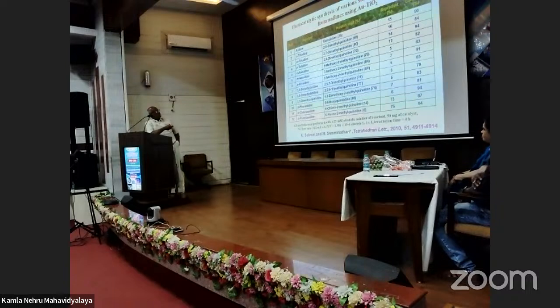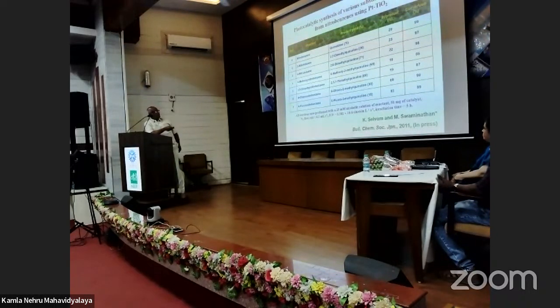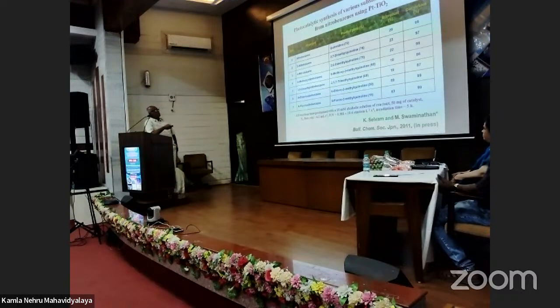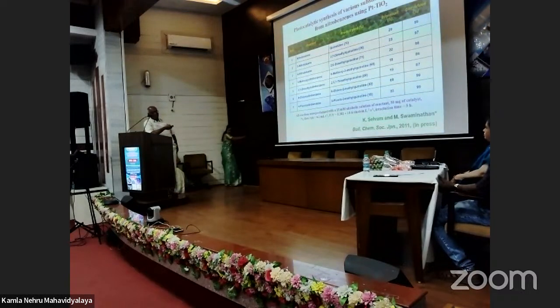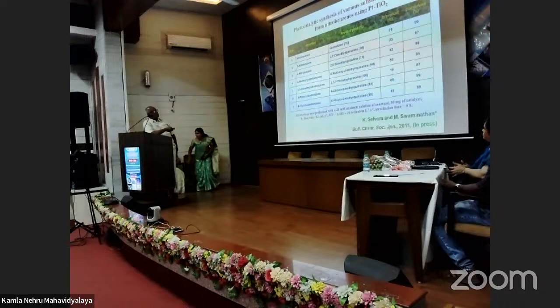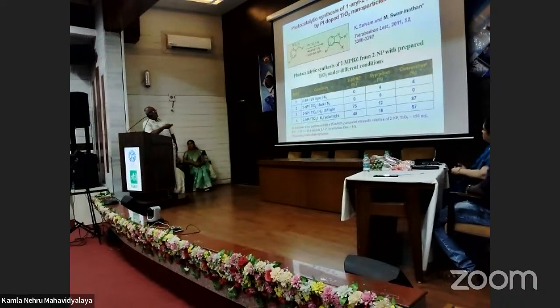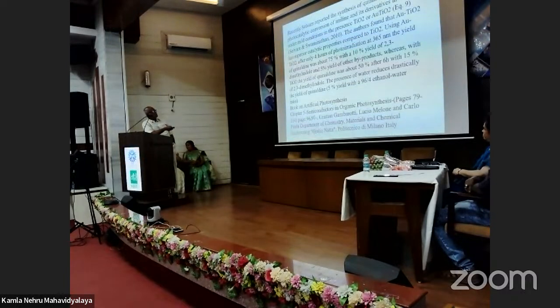And similarly, it's not only nitrobenzene; we can also take aniline directly with the alcohol, and we get the same product. And here the nitrobenzene with platinum TiO2, the same reaction was performed with platinum TiO2. And here these nitrodiphenylamines were taken to the platinum TiO2, and they also prepared this with platinum TiO2 and performed the experiment with solar light.